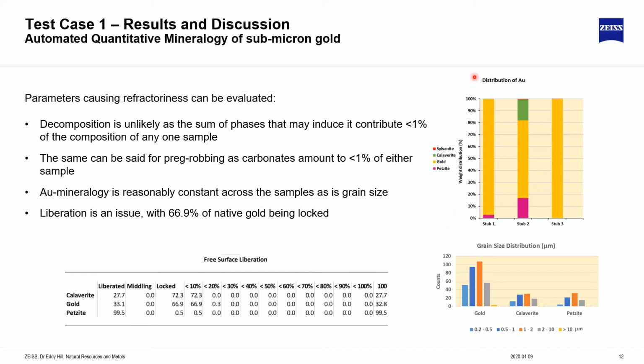On the right-hand side, we have charts for the distribution of gold between the three samples. And it's obvious that in stub 1 and stub 3, very dominant is native gold. In stub 2, we have some petzite and a contribution from calaverite in this sample too. Immediately underneath, we have a grain size distribution, and this ranges from 200 nanometer grains up to larger than 10 microns. Obviously, gold is the more present phase, and the majority of the gold appears to be present in the 1 to 2 micron grain size. And this is similar for the calaverite and the petzite. However, there are significant contributions at sub-micron size also.